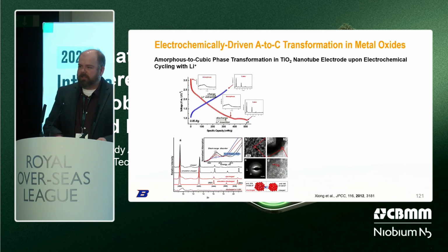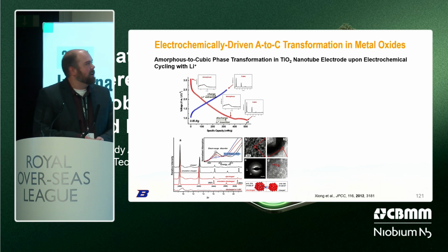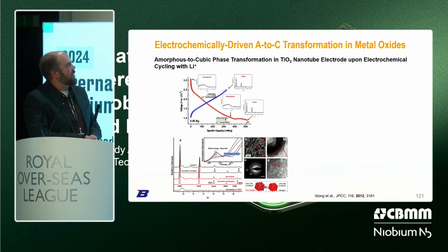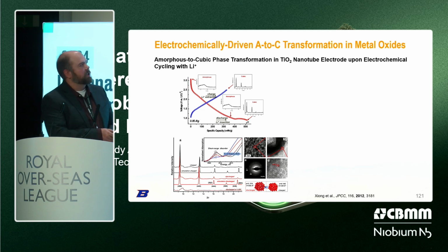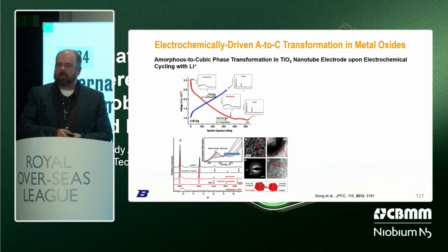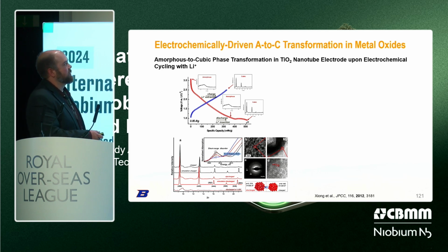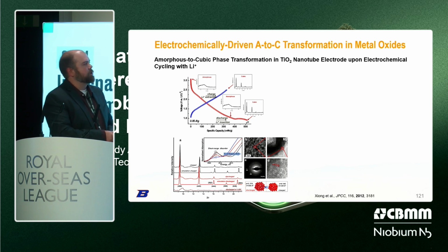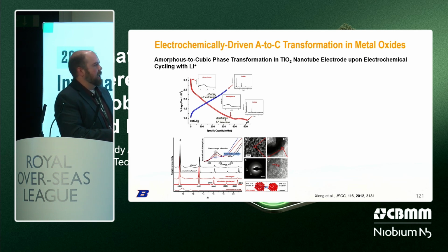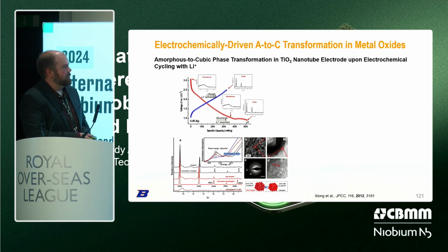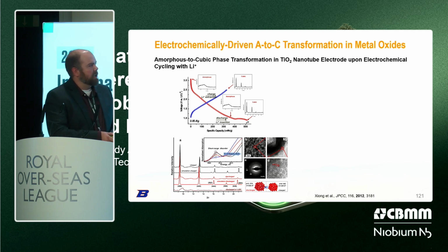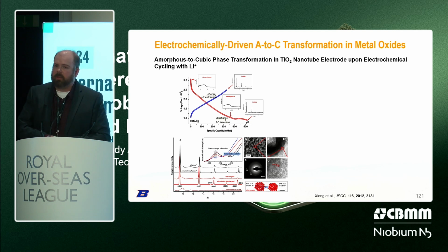Talking about standing on the shoulders of giants, Claire, my PI, had done previous work on TiO2 where she noticed that if she cycled at a certain voltage, she would get a phase transformation of the material from amorphous to cubic. She demonstrated this by XRD and TEM to show that the TiO2 nanotubes participated in this phase change.